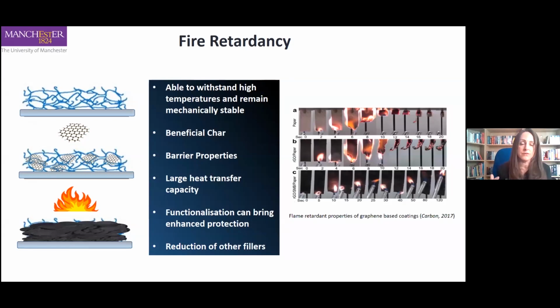And it's another example of graphene being a barrier. This is a physical barrier that prevents the transfer of heat down to the surface underneath, or it prevents transfer of unwanted combustion products through the coating back out into the atmosphere. And it's back to this tortuous path phenomenon again. It's a barrier effect. And graphene's very thermally stable, and this carbon scaffold acts as a template for this char formation.